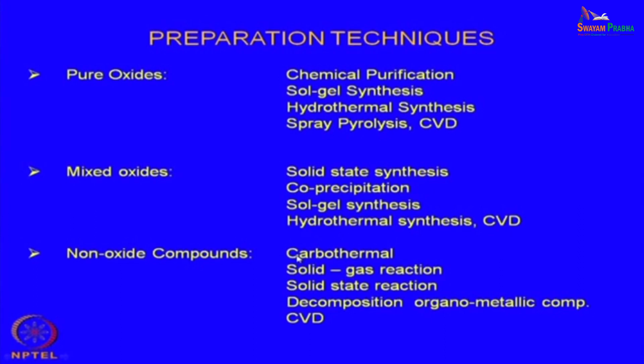Instead, we go for carbothermal reaction. Basically, carbothermal reaction is an oxide mixed with carbon and heated to high temperature. It is normally an endothermic reaction, and by that process the metal carbides can be formed. That is a very common technique for making carbides, whether it is silicon carbide, tungsten carbide and so on. They are mostly made by the so called carbothermal process, which is nothing but mixing with carbon and then heating it